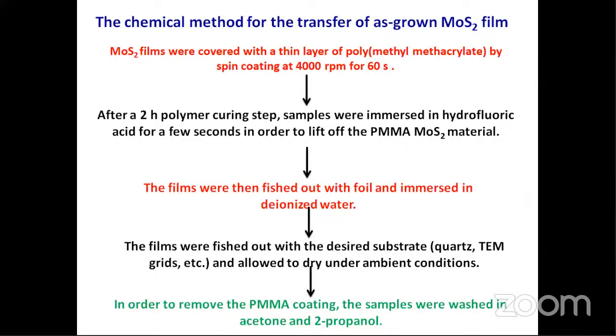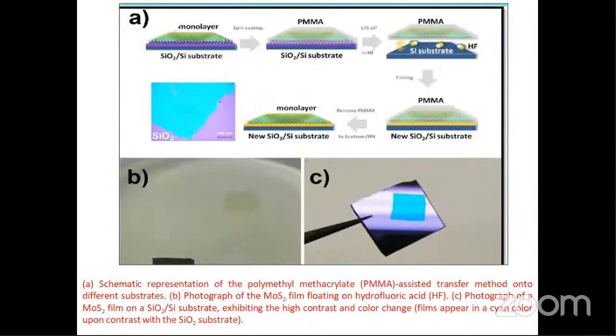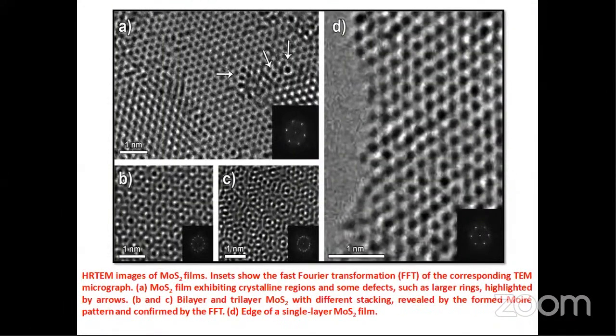One of the most important and tedious things in a CVD system is that after we synthesize with the help of CVD, the transfer of the film is very important. If you want to utilize that sample for transistor devices, it is very difficult. So for this purpose, we coat our as-grown MoS2 sample with PMMA, and after that we shift it in HF, which easily peels it from our substrate, and finally we deposit it on silicon oxide for the device process. Here is the HRTEM image of the as-synthesized sample.